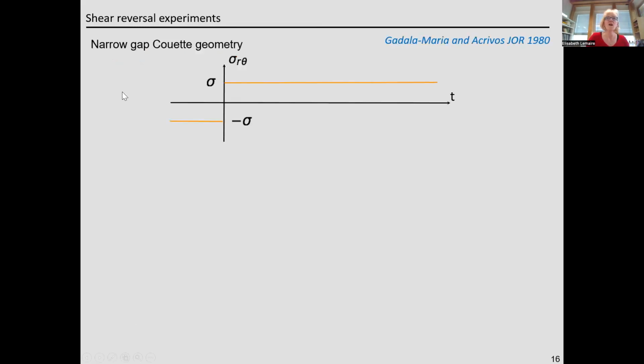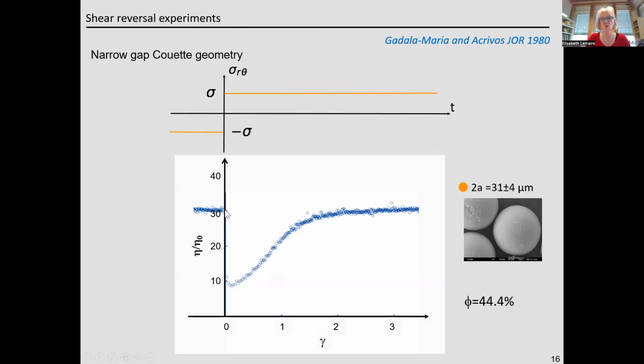The shear reversal experiments are a very good way to evaluate this contact part of the viscosity. The shear reversal experiments are very simple experiments, first proposed by Gadala-Maria and Acrivos in 1980. These experiments consist in shearing a suspension in one direction, and suddenly we reverse the flow direction. And we observe the transient response of the viscosity. When the flow direction is reversed, the viscosity falls, passes through a minimum, and increases again to reach the value it had before the shear reversal.